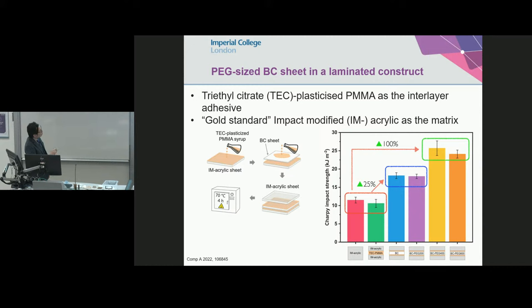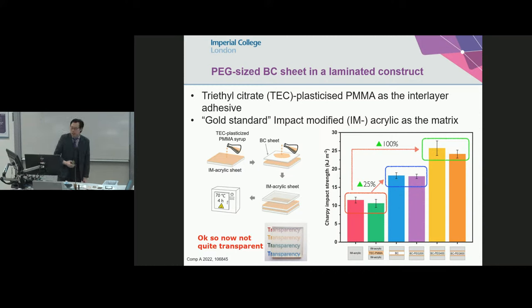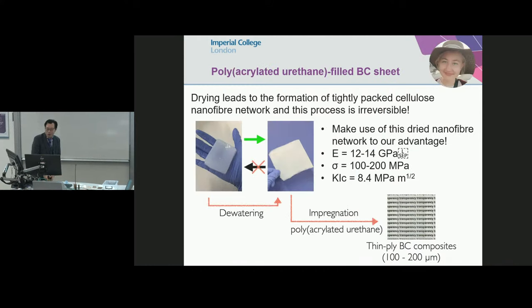So this is your unreinforced sample, so pure polymer, no reinforcement inside there. You can double it quite easily with the right type of polyethylene glycol that you are using. So that's great, but there's only one problem there. It's no longer transparent all of a sudden. So that sort of pushes us back to where we start. Because again, the polyethylene glycol system wasn't the right refractive index with the cellulose, so it's not transparent anymore.